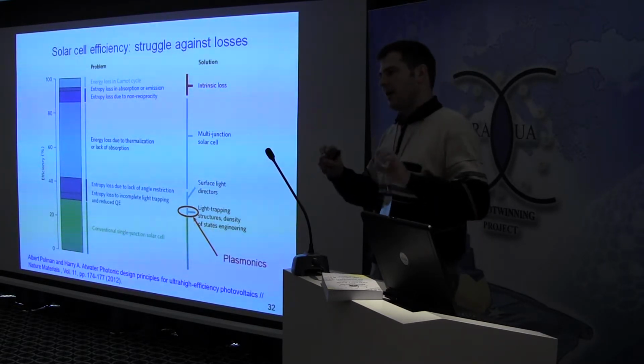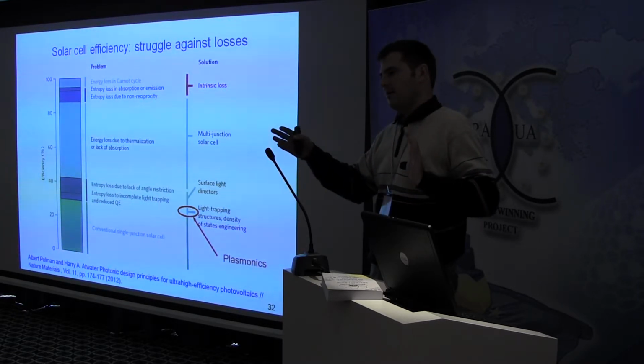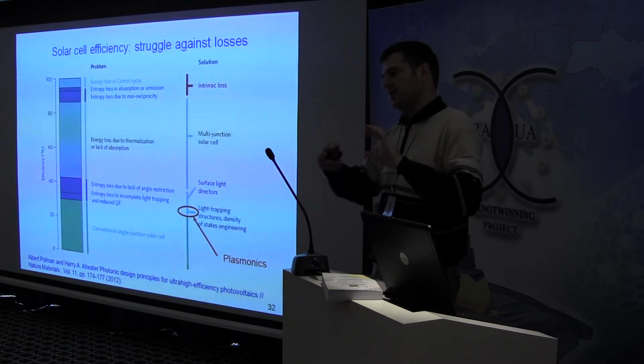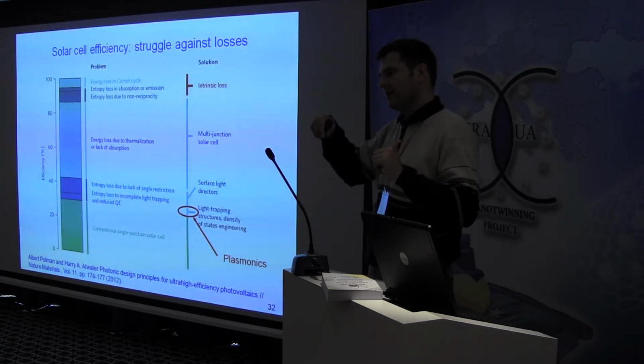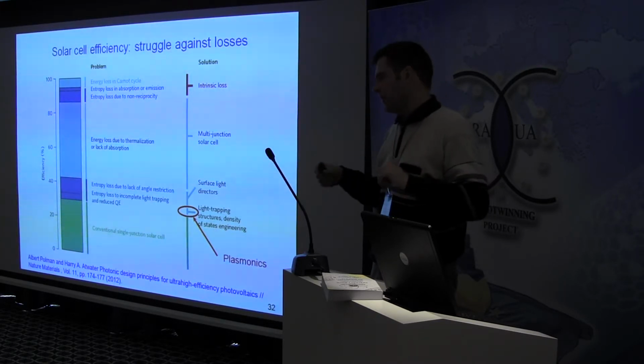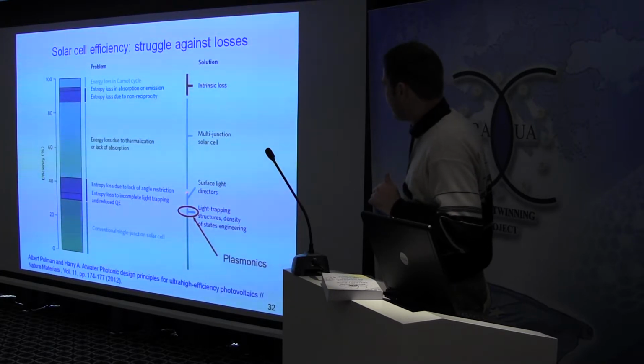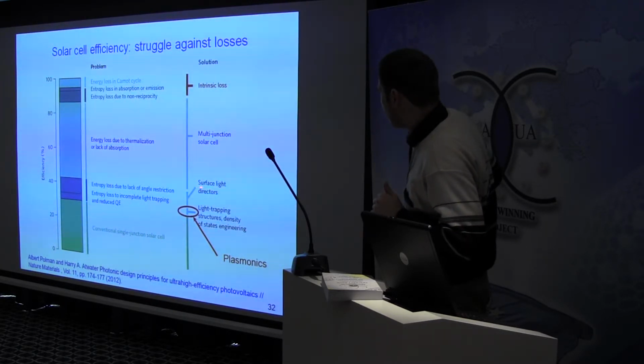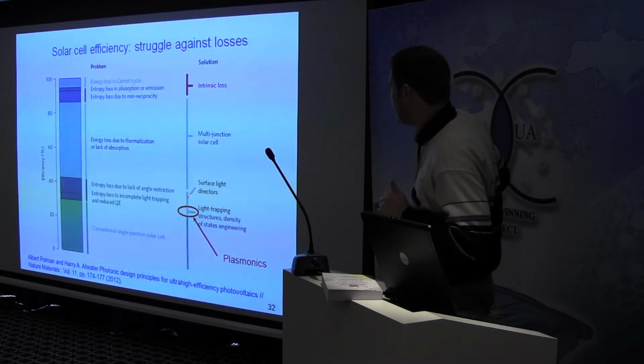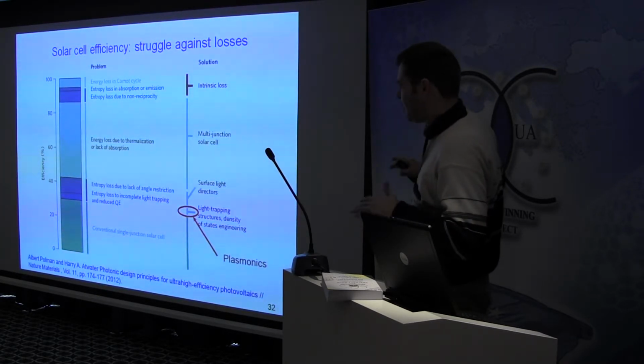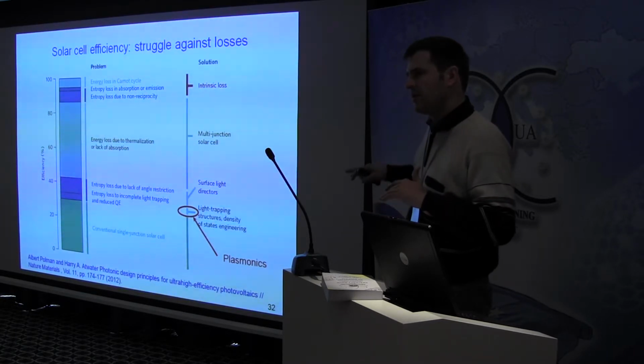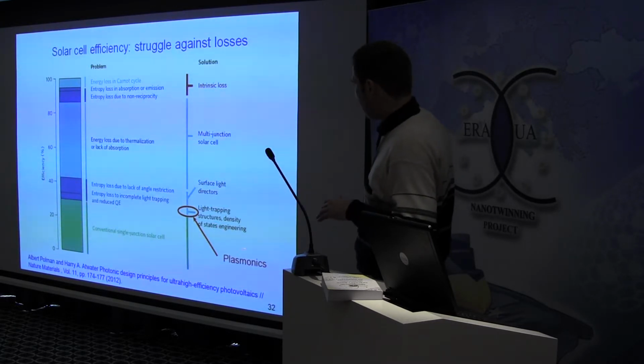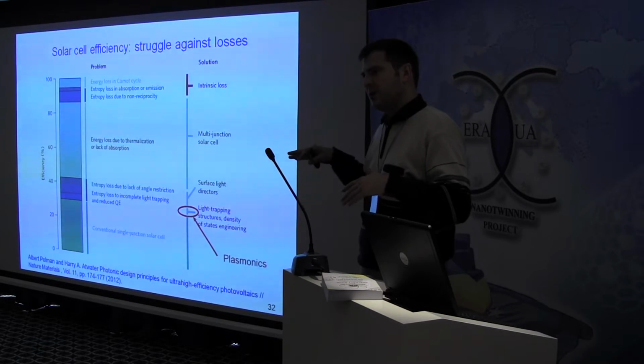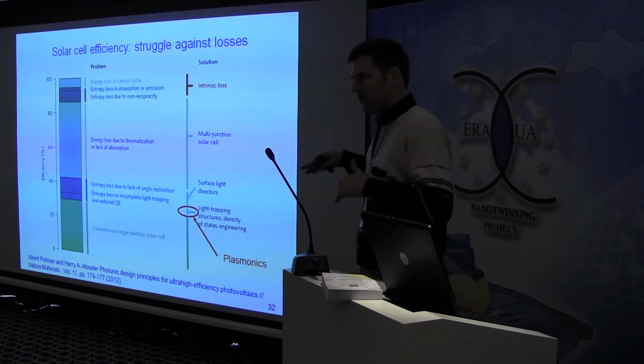It means that when you have several layers specially adjusted to absorb some spectral range of light, and these layers are deposited one after another, we can step by step absorb one region, then a second, then a third, and absorb the light more completely. And you see these multi-junction solar cells can increase efficiency by several tens of percent. Then light directors can also give us near 10%. And plasmonics is situated somewhere here, it means up to, I think, 5% we can obtain using plasmonics. And for perspectives, I think that if we combine plasmonics with light directors or with multi-junction solar cells, we can obtain more. So this plasmonic technique can help us in combination with other techniques.